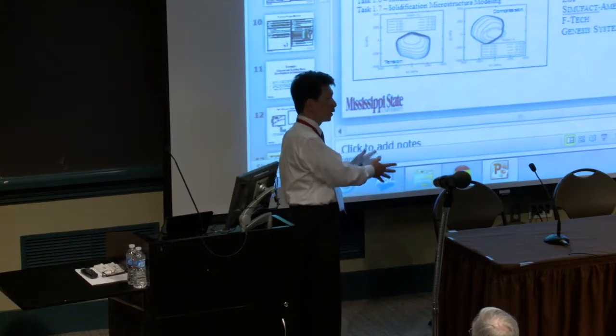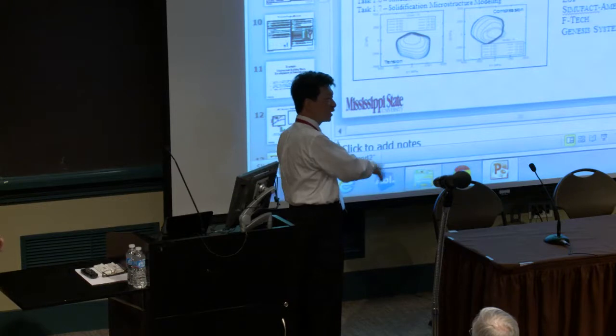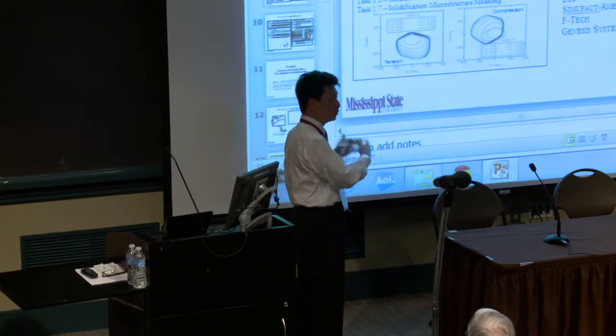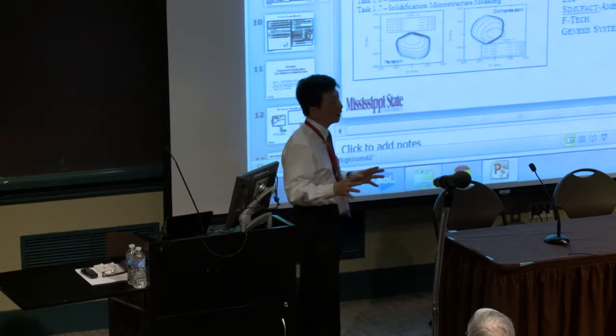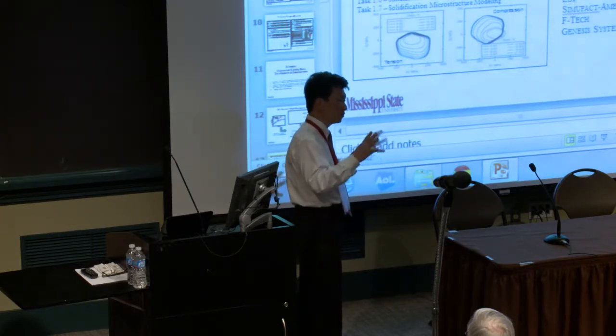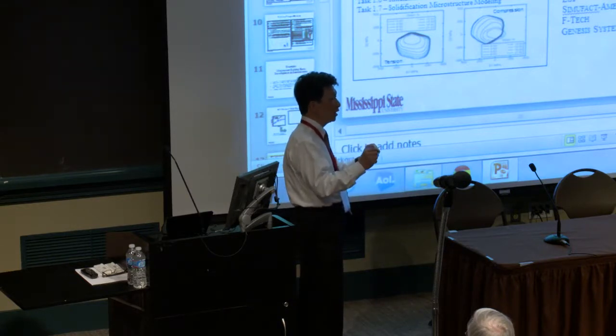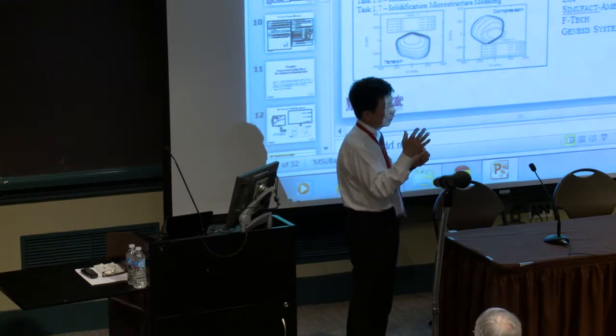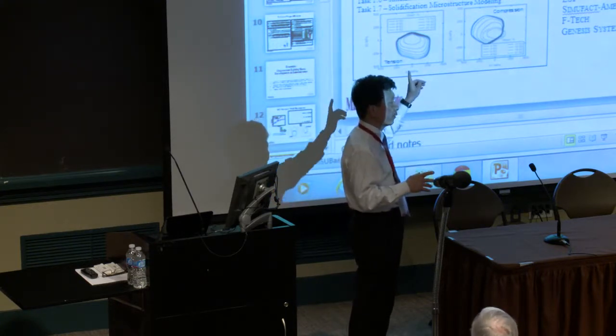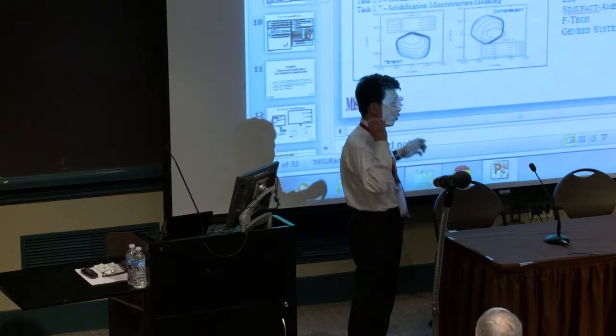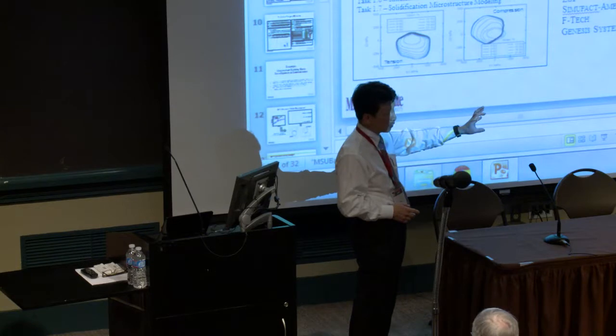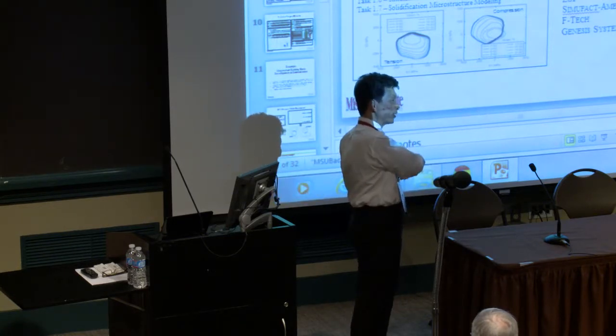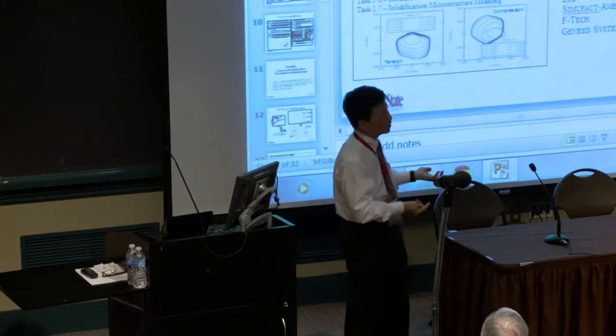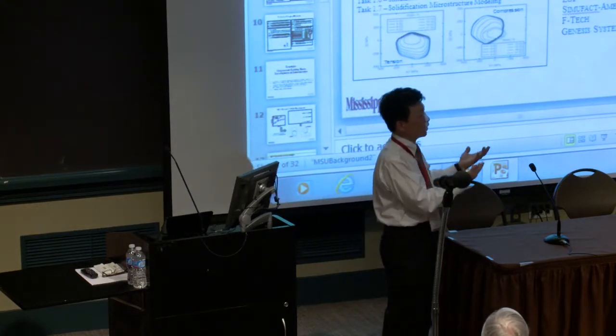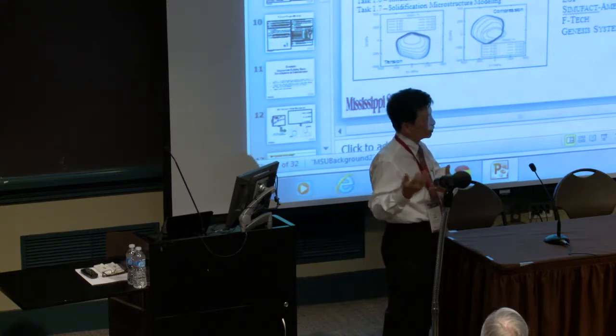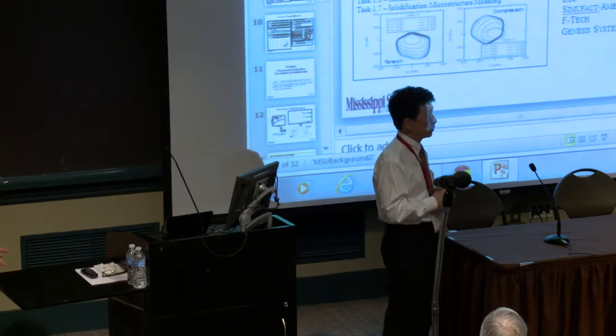Is this dislocation based, or does it have to be dislocation and twinning based together? Even in the self-consistent flow, we're still improving that area. But simultaneously, we're already proving that we can closely describe certain textures and initial yield strength in the moderate extrusion ratio and the sheet form. But then we found the texture becomes very diffuse when you do large extrusion, where we have dynamic recrystallization. So now we have to look at the crystal code and see if we can introduce dynamic recrystallization into the model, and how that information can feed into the ISV model. Those are in progress, and we can talk about the details afterwards.